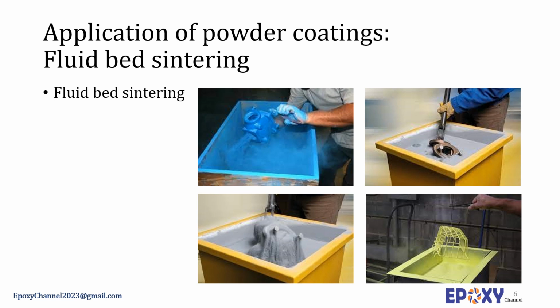Upon contact, the particles melt and form a film at the surface of the object. The temperature and the heat capacity of the object, the melting temperature and the particle sizes of the powder, and the dipping duration control and determine the thickness and the quality of the obtained films. To complete the process, the object is then placed in a stove where the film formation is completed. Therefore, only heat-resistant objects with limited sizes are suitable in this process. Thicknesses in the range of 80 to 400 micrometers can be reached by fluid bed sintering powder coating.